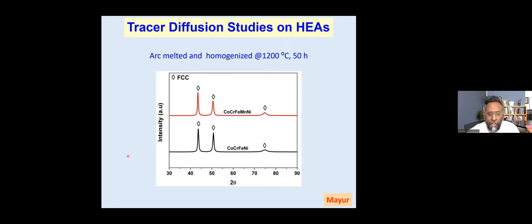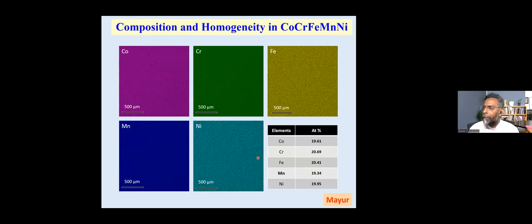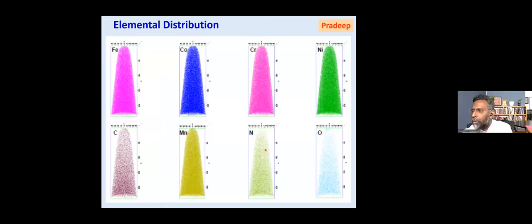So we made two alloys, of course, a large number of alloys we have studied, but I'm just showing you two alloys here. One is a five-component alloy, another is a four-component alloy, and you try to see whether they are single phase. You see X-ray diffraction, they happily show you a single phase. You do what is called elemental mapping in a SEM, EDS mapping. Again, you see everything is very uniform. And then you also do atom probe to find out at the atomic level whether they are uniform or not. Again, you see they are all very uniform.